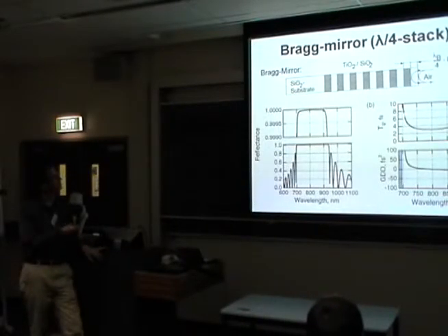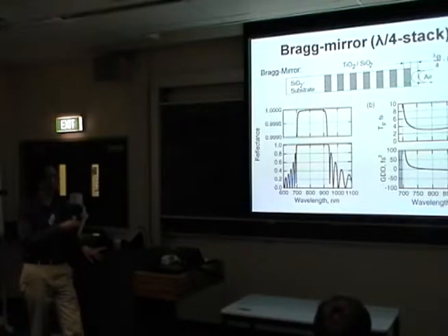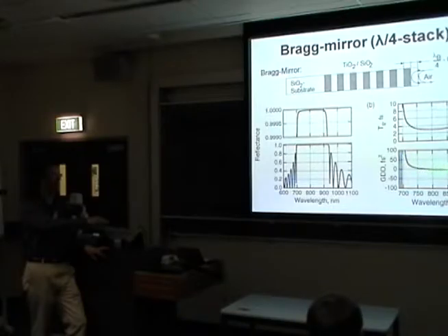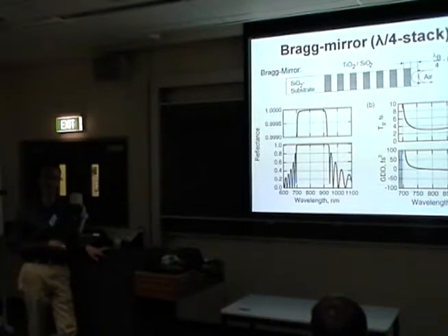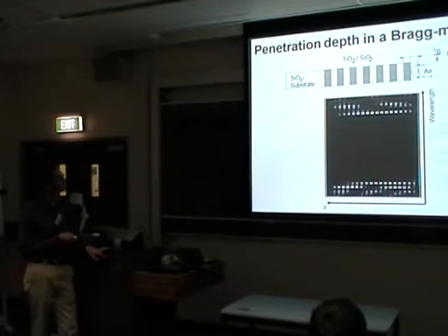So here are the properties of a normal Bragg stack. The center frequency gets high reflection, and then I get a certain stop band in which all the colors get reflected. For titanium dioxide and silicon dioxide, I get high reflectivity essentially over about 200 or so nanometers. The dispersion, I have no influence over it. It has no group delay dispersion in the center, but as I go away, it has some group delay dispersion. And you remember the sapphire crystal also had the same slope, so it's actually bad that I'm left with some dispersion.